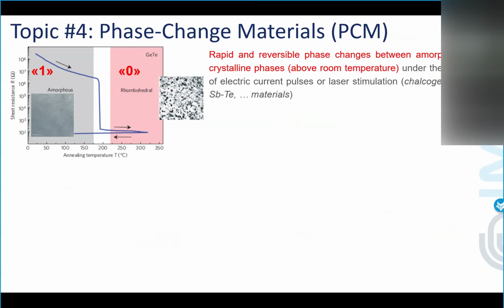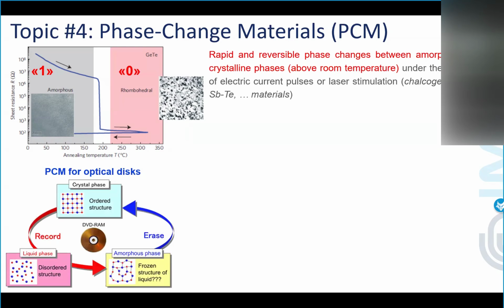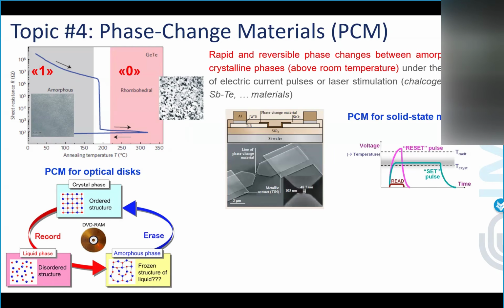with a final example where we use Emission Mössbauer spectroscopy in some topics that are mostly connected to solid-state physics and material science, which are phase change materials. Phase change materials, probably you are aware of that, show a rapid and reversible resistive switch from high resistance in the amorphous state to low resistance in the crystalline phase, and they are used for memories. When we were used to DVDs, optical discs, phase change materials were at the basis of this process, but nowadays ST actually uses them for solid-state devices. So it's a very interesting material.